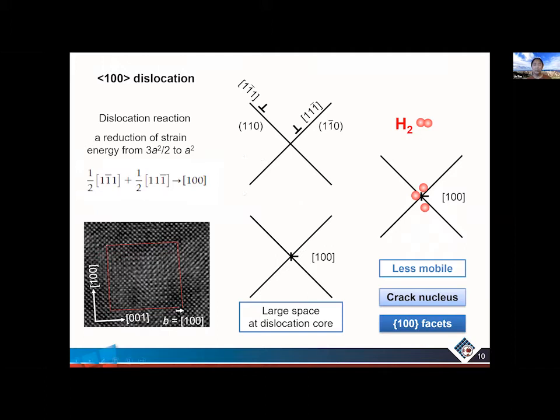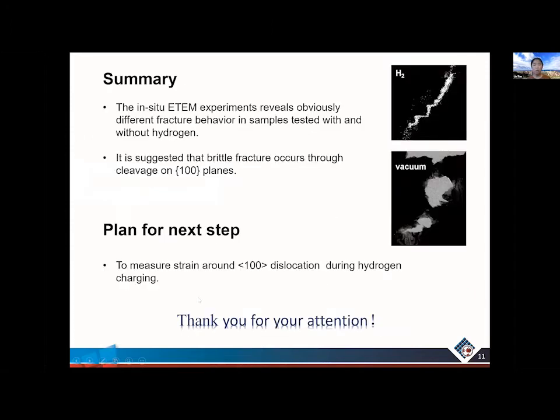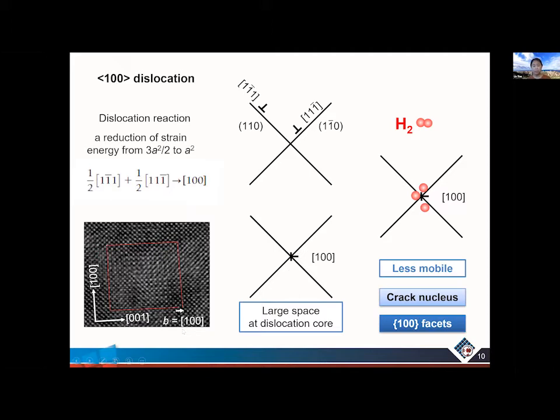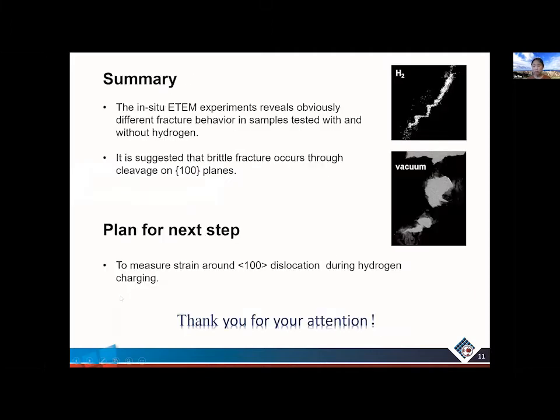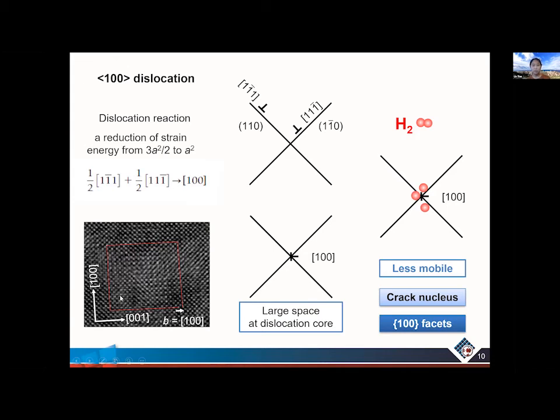So this is related to 100 dislocations. We know that in BCC materials, most of the dislocations are of 111 type. But during deformation, 111 type dislocations could react and create this 100 type dislocation. So even in our TEM samples, I can find 100 type dislocations, showing here in this high resolution TEM image. And this figure here shows how the reaction takes place.